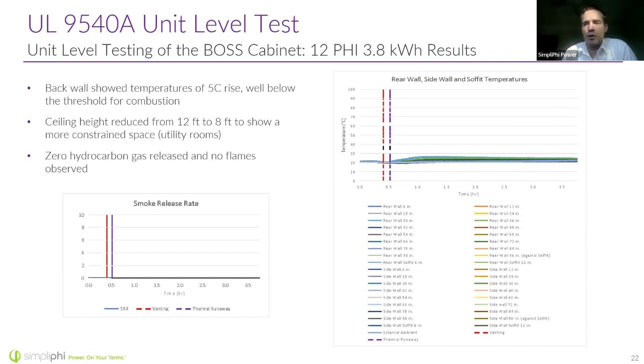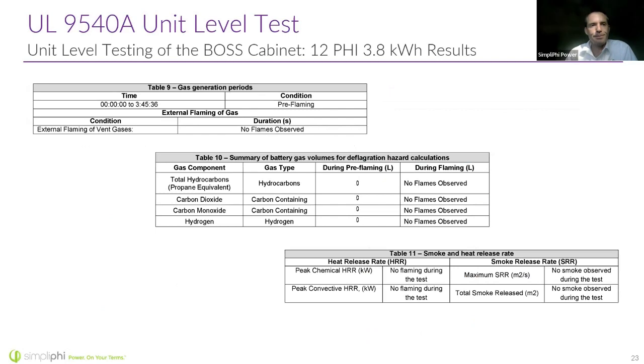So we're looking at the temperature of those plywood walls around the battery banks. And you can see that they really didn't heat up much there. They were only going slightly above room temperature. So not a lot of heating occurred in the room where the batteries were installed. And they were monitored in many different locations. Even though we're noting the smoke release time there, we did see a slight rise in the temperature of the walls, but we're only looking slightly above room temperature.